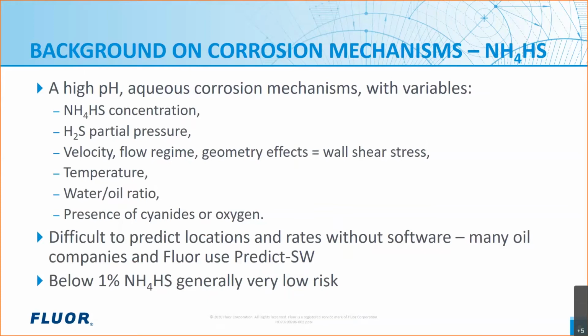So ammonium bisulfide corrosion is a high pH aqueous corrosion mechanism. And that's unique because in the corrosion engineer's world, most corrosion mechanisms occur at lower pHs, but this is one unique one that occurs at high pH. It has many variables that you need to review in order to know where it's going to occur and what the corrosion rates are going to be. The variables include the ammonium bisulfide concentration, H2S partial pressure, the velocity and flow regime. They combine to give you something called the wall shear stress. That's really the key variable that we track for determining the corrosion risk.